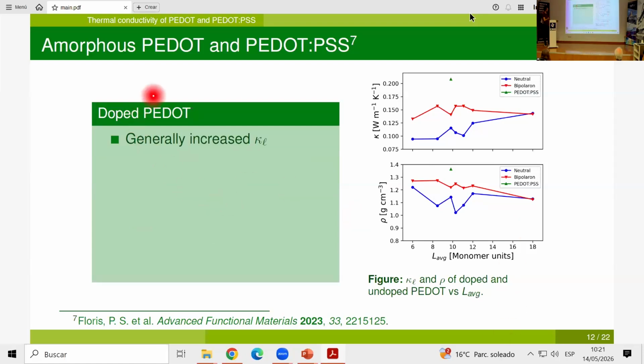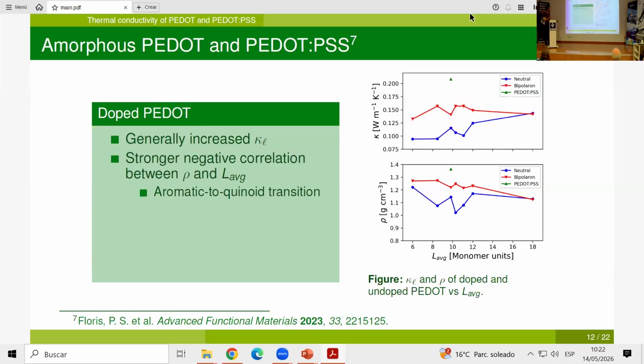And when we consider doped PEDOT, this is the red line here, the K is generally increased, but it is not increasing with respect to the average length of the chains. Instead, there is a peak around here for intermediate chain lengths, and then it starts to decrease again. We can also see that the density is quite evidently decreasing with the average chain length. And this is ultimately due to the aromatic to quinoid transition that PEDOT undergoes upon doping.